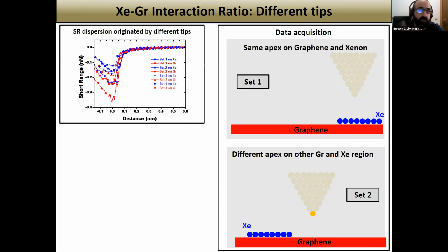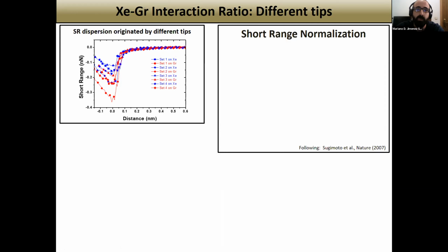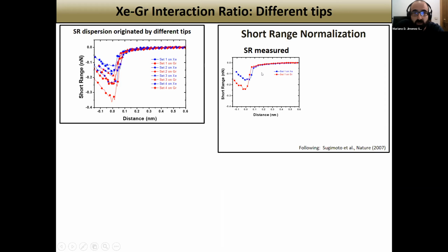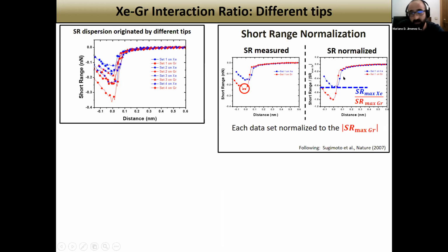So how can we treat this dispersion in order to measure the relative interaction rate? Well, we can use a normalization. How? As an example, I show you the process with the first set of data. The idea is to normalize each set of data, I mean, the data acquired with each tip, to the maximum attractive force measured on graphene, I mean, to this value. And what do we obtain from this process? Well, we obtain plots like this, in which if we look at the maximum attractive point on the xenon curve, we obtain the relative interaction rate between xenon and graphene.